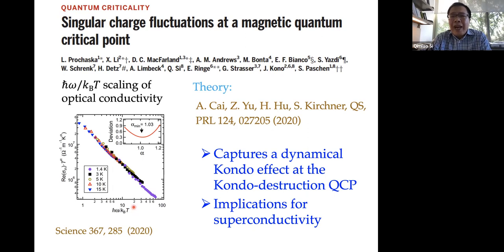And so the very large amount of quantum critical fluctuations, which one would think are primarily in the spin sector, because these are local moment based systems as described by the Kondo lattice model, and as the entropy that's measured in the quantum critical region testifies, there's a very large spectrum that's manifested in the quantum criticality. This experiment is significant in a number of ways. Microscopically, we believe that it shows that even though the Kondo effect in the static sense is destroyed, in the fluctuation sense, it's still operating.